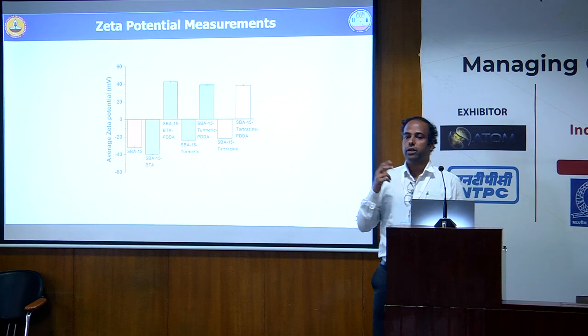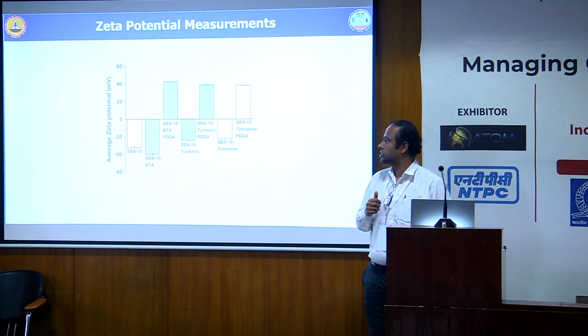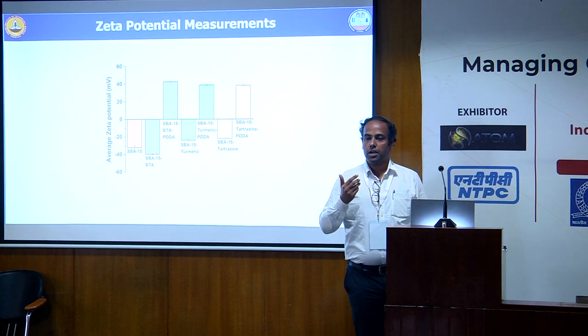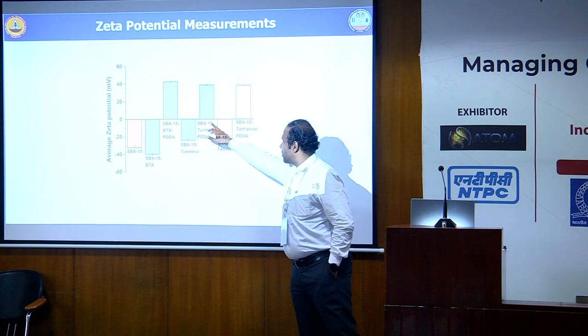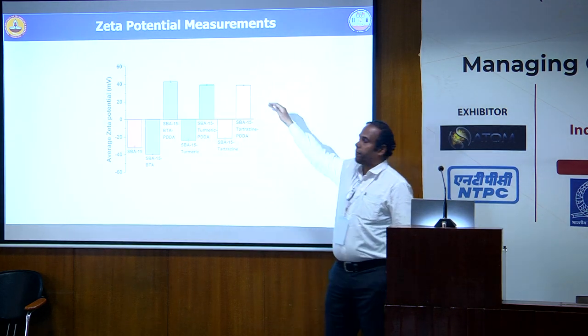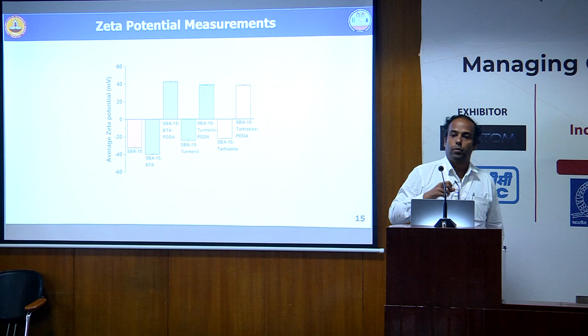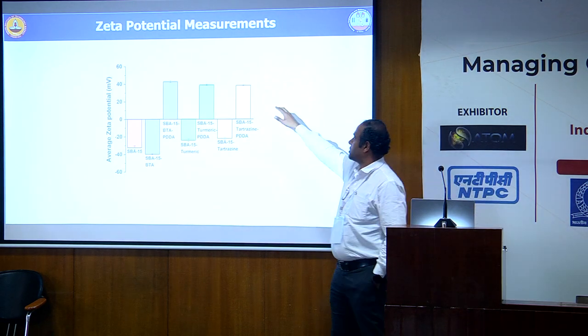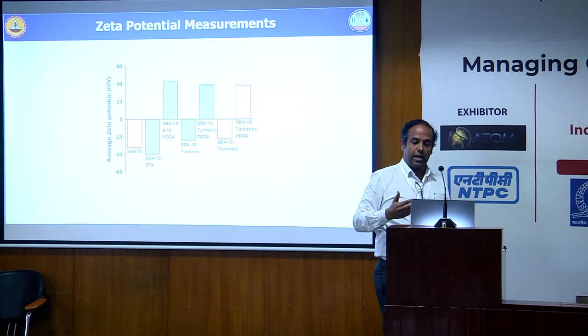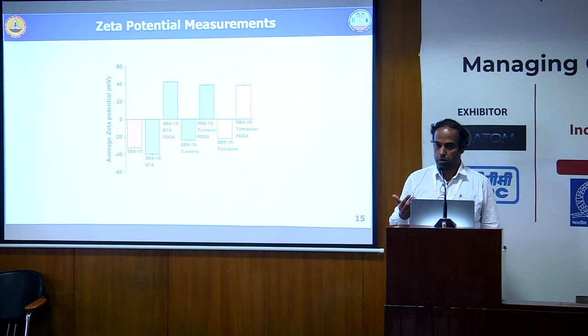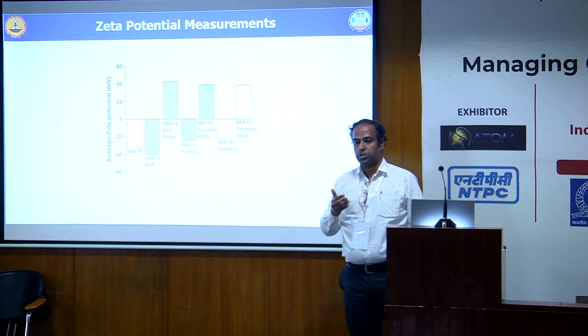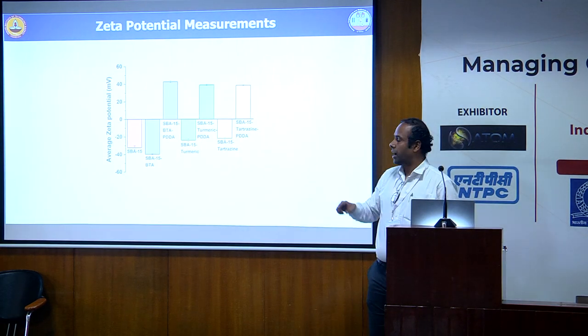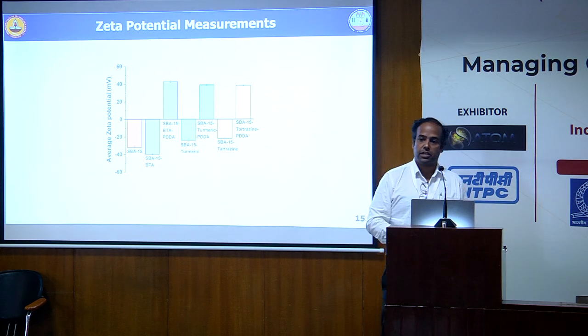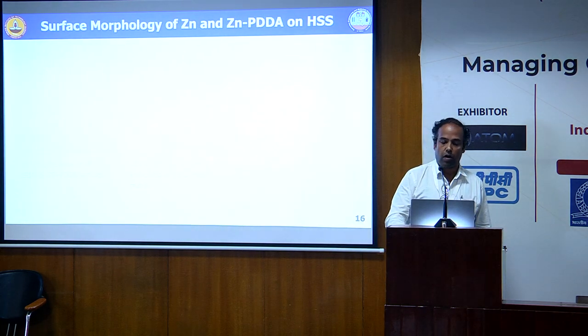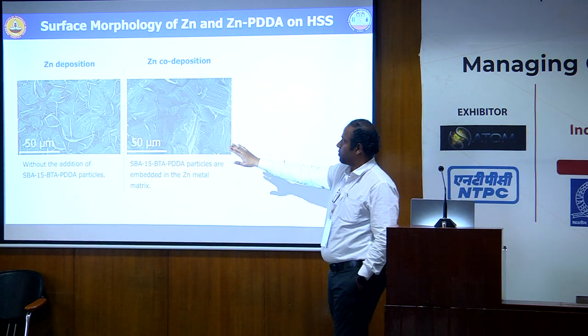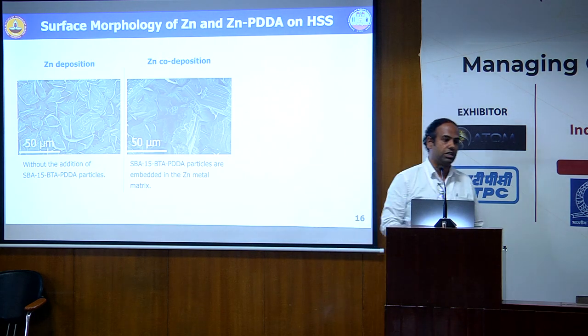You need to play with many forces, and one of the forces is the charge which is developed on the surface. So luckily for us, when we modified this with PDDA, the surface charge of these particles when dispersed in the liquid is approximately positive. So by nature, they would tend to go towards the cathode. So when I do electro co-deposition of zinc from a zinc bath, dispersing these particles in it, it is possible to co-deposit. This is a surface morphology on the left, which shows a typical zinc structure.